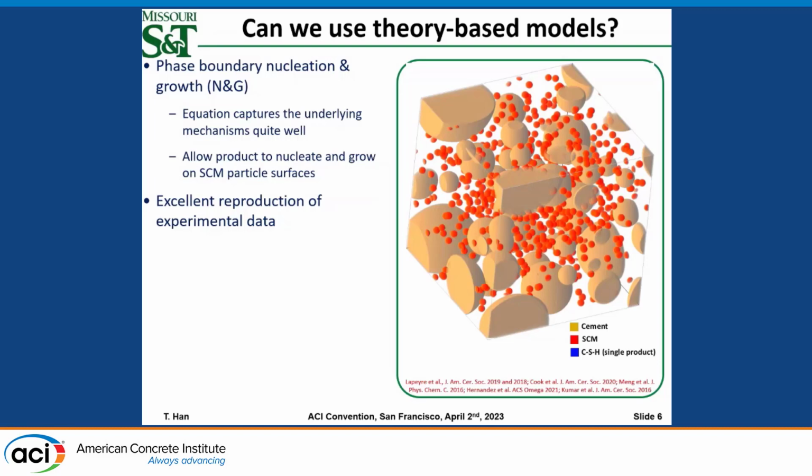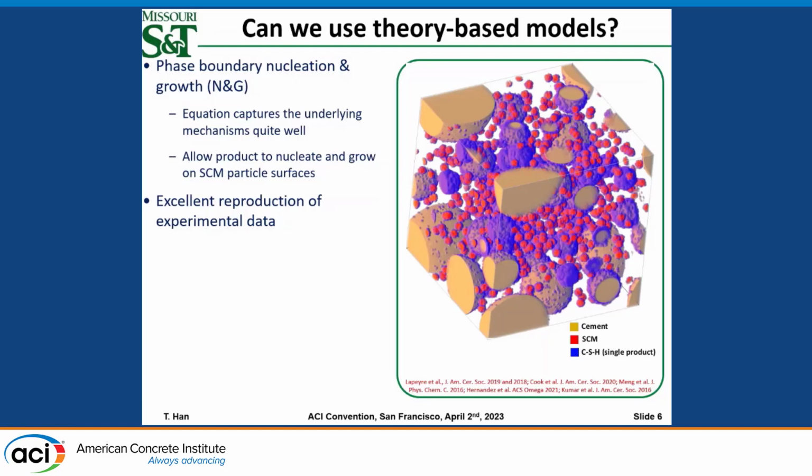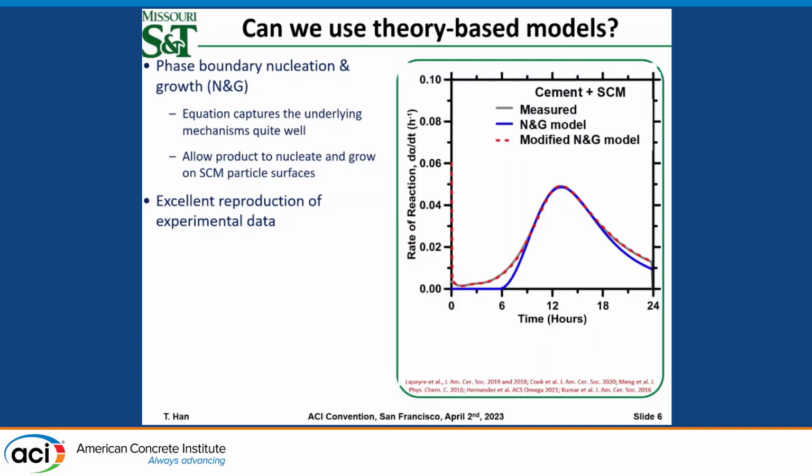In this model, it accounts for the cement and SCMs, and the cement hydrates grow on the surface of those particles here. And this is the simulation result. You can see the nucleation and growth rate model produces an excellent fit to the measured values here.